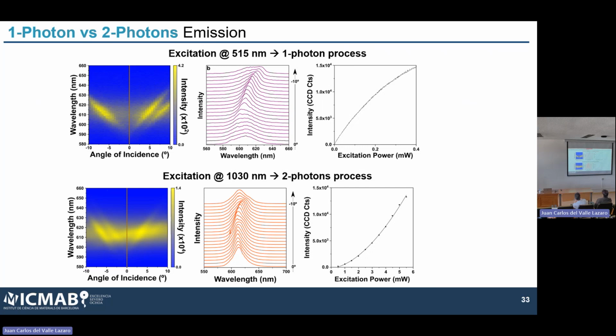And again, we believe this is due to the fact that here we are also exciting all the plasmonic components, and all the components of the quantum dots are excited at the same time. So this is a much more complicated light-matter interaction. Here instead, at 1030 we can actually go to much higher excitation power. At 515, if we go above this, we burn the system immediately, while in this case, since we're not exciting the localized plasmon, we're not generating heat, and so on and so forth, the system is much more stable.